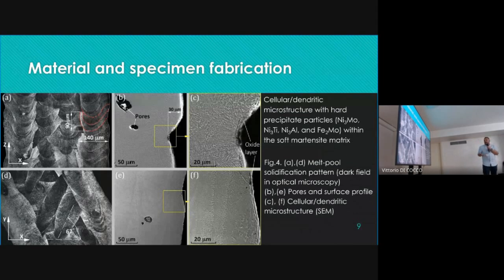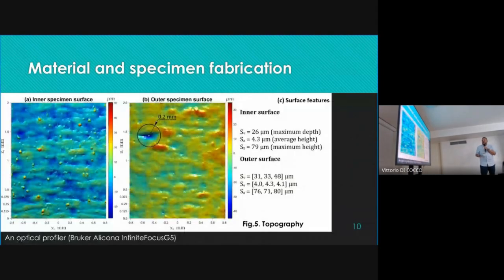So for the next slide, this is the optical profiler data from the specimens. On the left, you can see the inner layer of the specimen, on the right, the outer, and the valley on the right side is clearly seen here, the blue hole in it. On the left, you can see spots of reddish color. This is not actually the specimen; those are residuals of powder that stick to the specimens. And even though we use the shot peening, cleaning of the inside of the specimen was not sufficient. It didn't have a net impact on the fatigue life, but it was there, and it can be seen here. But the surface parameters are fairly similar for both the outer and inner layers.